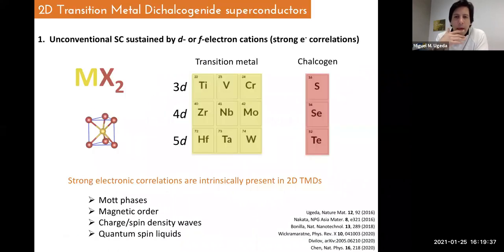Okay, let me go point by point to show you these common characteristics are satisfied in TMD superconductors as well. As I said, in general, unconventional superconductivity is sustained by d or f electrons, which is what happens here. In particular, these are d electrons sustained by, for example, titanium, niobium, or tantalum. It's well known that these d electrons lead in TMD materials to strong correlations. And the fingerprints of these strong correlations in 2D materials are the presence of Mott phases, charge and spin density waves, and the existence of quantum spin liquids. That's quite accepted in these materials already.